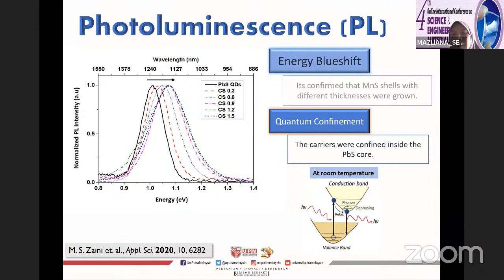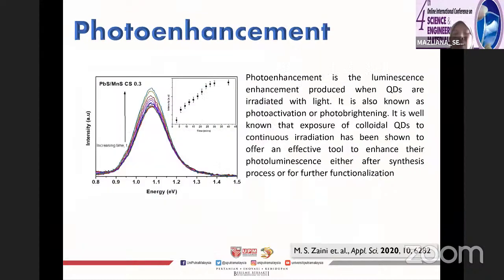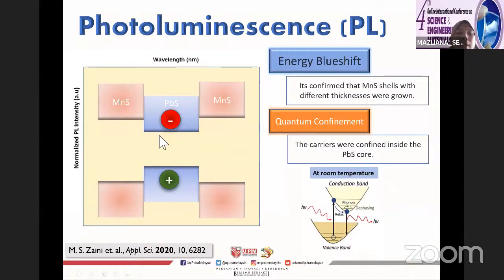The blue shift confirms the MnS shell growth at different thicknesses, and this is due to quantum confinement. As I mentioned before, our quantum dot is type 1, and the electrons and holes are confined in the PbS region. When we grow the shell layer, we sandwich the PbS core.